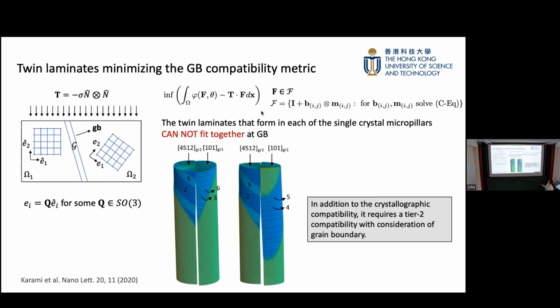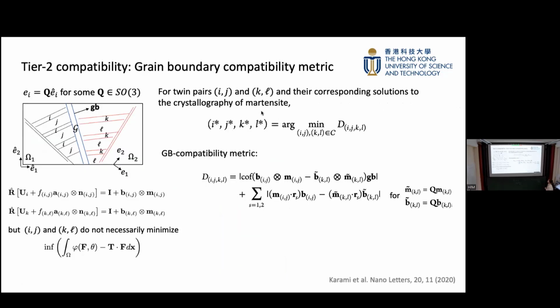Okay, so if this one is a good twin laminate on this side, and this one is a good twin laminate on this side, it doesn't fit. Then, in addition to the crystallographic compatibility that we discussed a lot in previous years, it requires a tier 2 compatibility that really needs to consider the grain boundary.